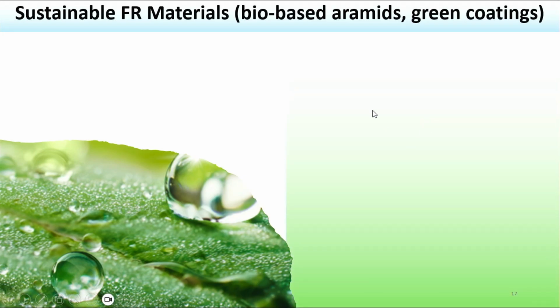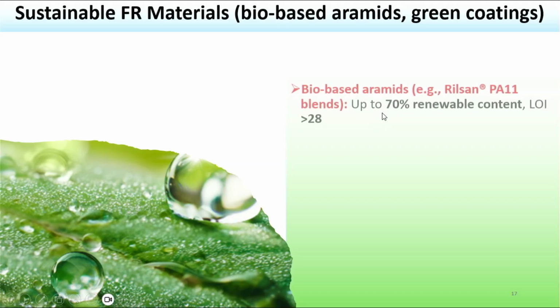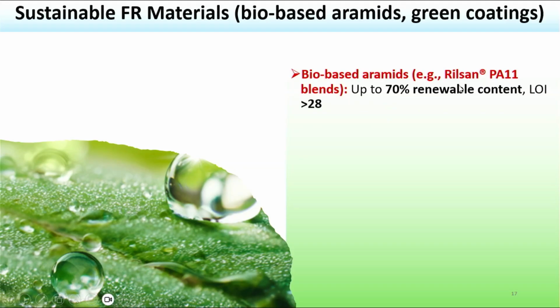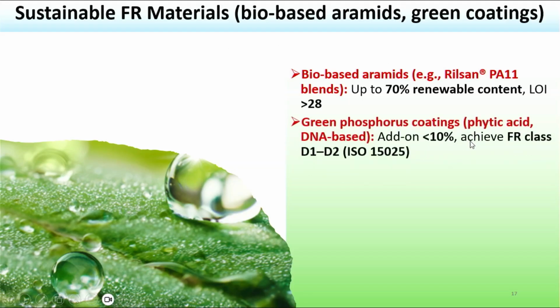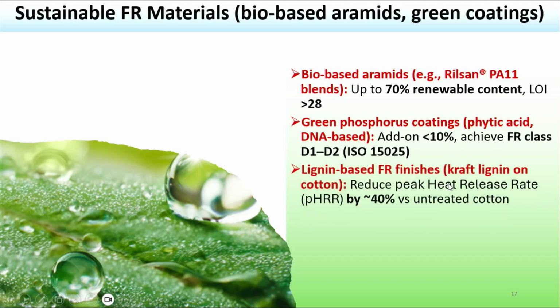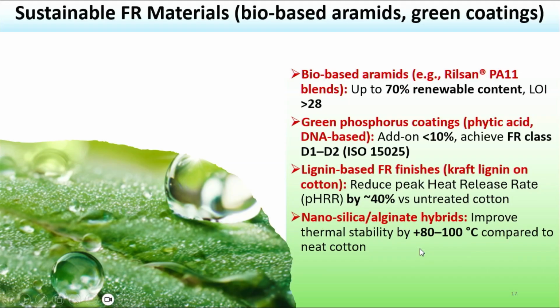Then sustainable material development: bio-based aramids have been developed, and green coatings. So, like you can see the bio-based Rilsan PA11 blends. So, that is actually bio-based aramid with up to 70% renewable content. LOI is more than 28, and green phosphorus coating, that can be used for FR class D1 to D2 as per ISO 15025. Lignin based FR finish can be used, and nanosilica and alginate hybrids can be used as a coating material to improve thermal stability.